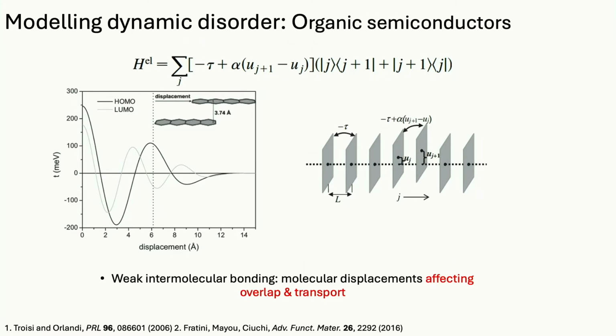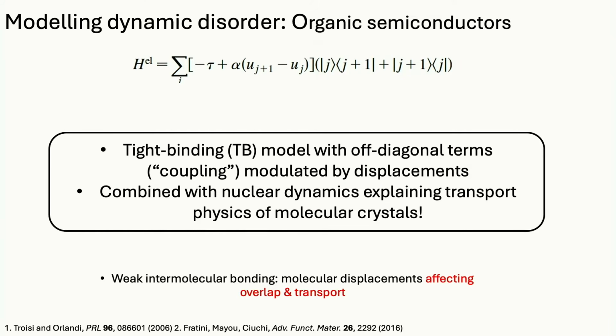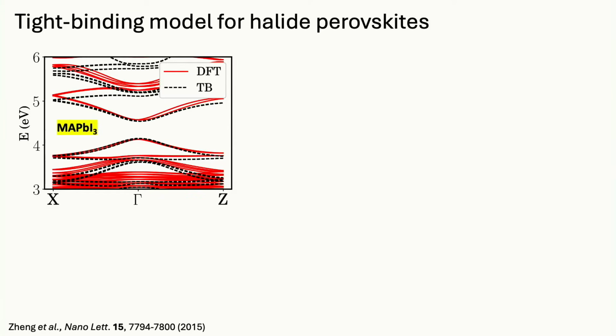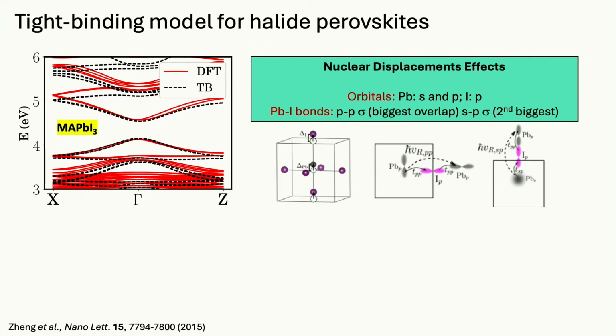So what we do is we try to model how the electronic structure is changing. If these rotations are going wild and distortions are happening, how does that affect the properties that we care about, like what's happening to excited electrons and holes when this thing is acting as a photovoltaic? So we make what's called a tight binding model, where we calculate the energy of putting an electron on any given site and the energy to move an electron from any site to another. We developed this tight binding model, and what you can see here is that it fits the bands near the band gap very well. So it's a good enough, simple model for what we want to do.